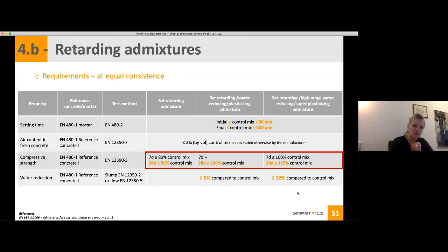Now, if you use a retarding admixture that also has a plasticizing effect, it means you will have also an effect on your strength. In the case of a plasticizing admixture, your strength at 28 days should be at least the same as your control mix. It can be higher, but cannot be lower. And if we look at a set retarding admixture that is also a super plasticizer, you should have a positive effect on both 7 days and 28 days strength. So at 7 days, you should have at least the strength of your control mix, and at 28 days, you should have a higher strength, 115% of your control mix.